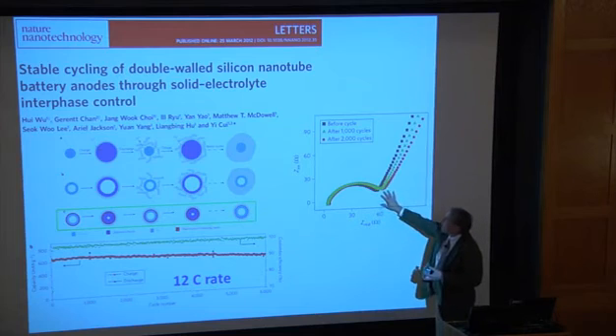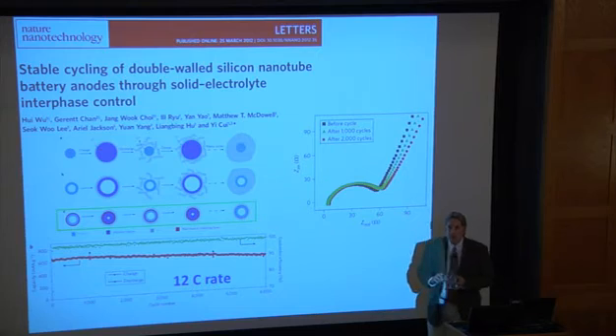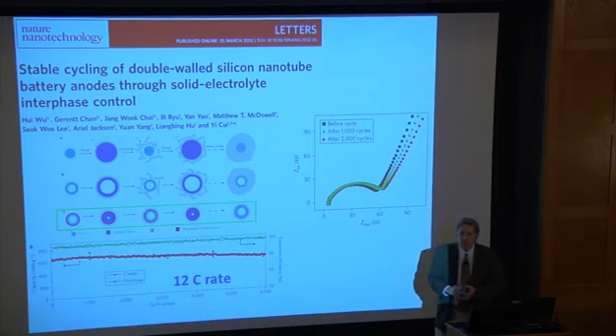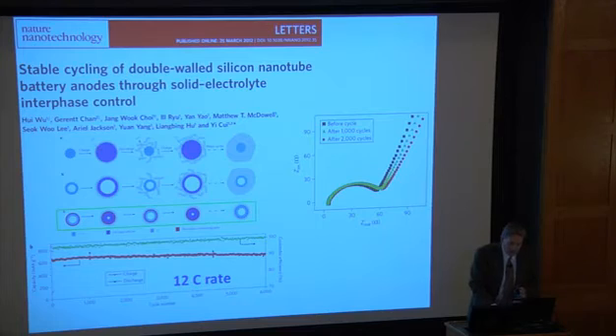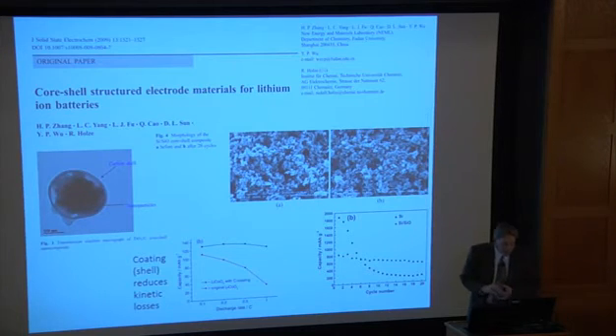These are some of their AC impedance results, and the point is that they're very stable. And when you look at this, those who work in this domain would tend to look at that and say it's a very stable electrode structure. And so it's quite promising in this short core shell configuration.